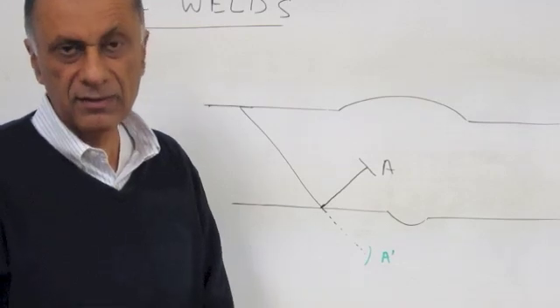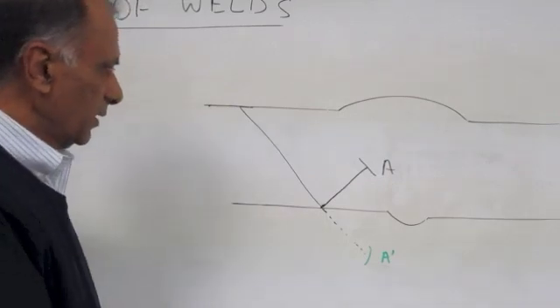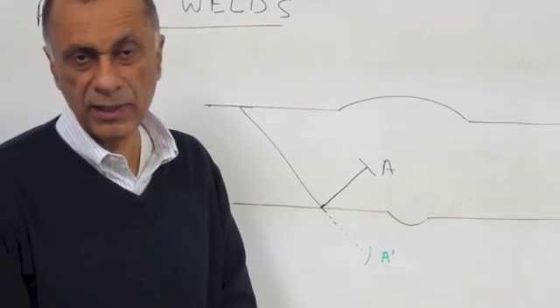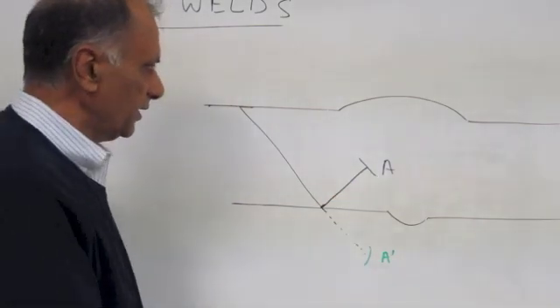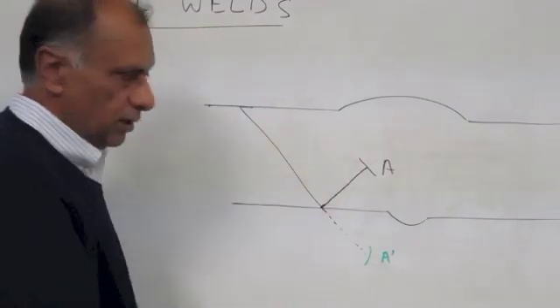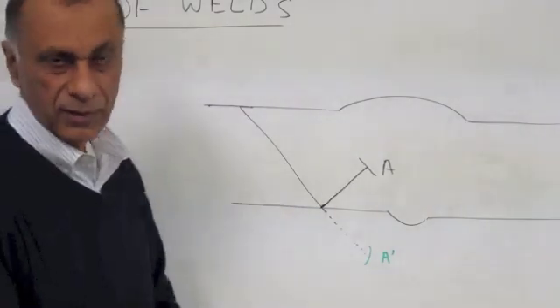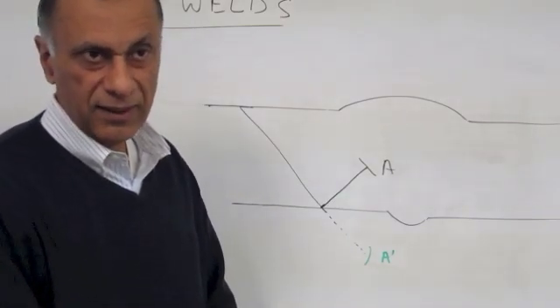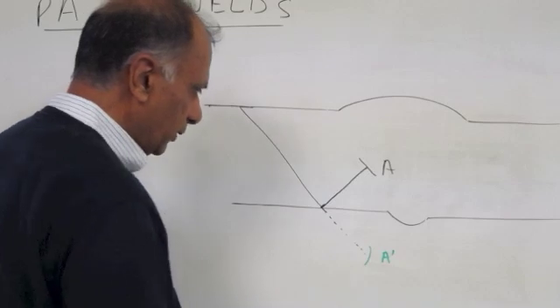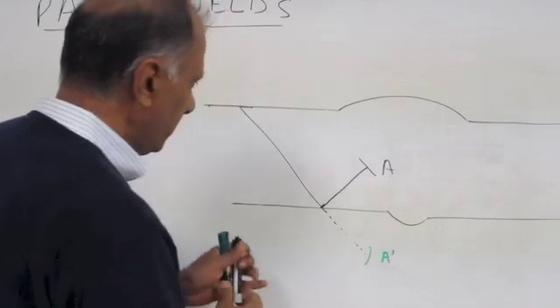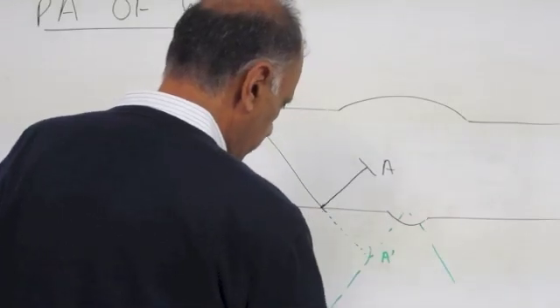So far we have been discussing phased array inspection in the first leg — from the probe straight down to the bottom of the plate. However, there are some flaws which we cannot see in the first leg. One example is lack of fusion at the side wall of the weld. The sound will travel to the bottom, get reflected, and then go back to the probe in the second leg. The phased array image will show this flaw at a flipped location — the image of the top, root, and plate essentially flips down, so the flaw appears mirrored below the bottom surface line.